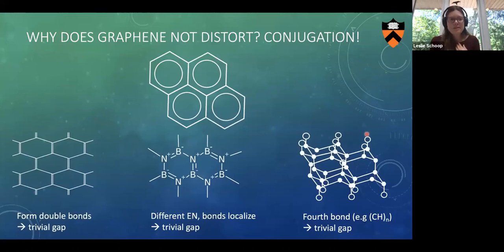So it's a very chemically versatile element which likes to bond to itself and do a lot of crazy chemistry, including having these fully delocalized bonds. And no other element is known to do that. And so there was a reason why early predictions of graphene analogues like silicene, germanene, stannene never really happened to be made, especially freestanding, because the same chemistry which is done by carbon is just not done by any other element.